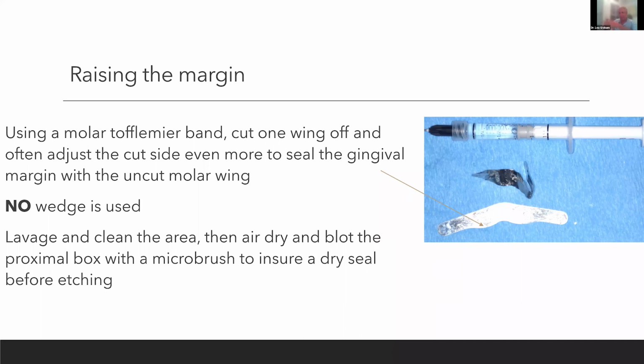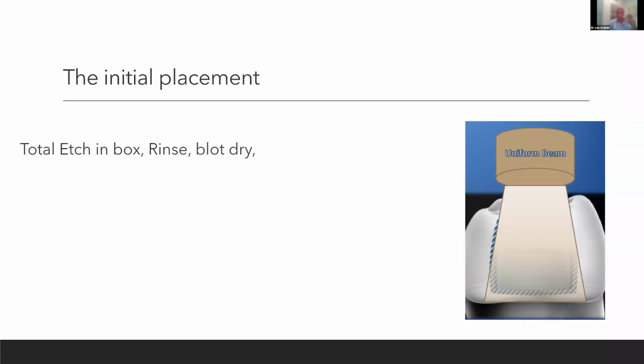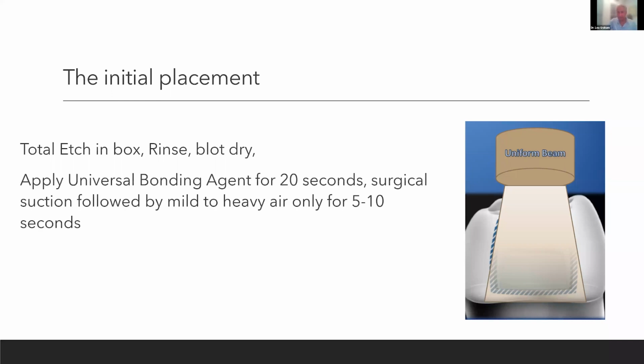Once your band is on tight, clean the area, rinse it, blot dry, and make sure your micro brush is not wet. That ensures you don't have any leakage, period. You're going to etch. Now you're going to rinse, blot dry, and again place your universal bonding agent. After blotting dry and placing your universal bonding agent, you're going from mild to heavy air for 5 to 10 seconds, and you're going to light cure for 30 seconds again, because you're far away from the light.